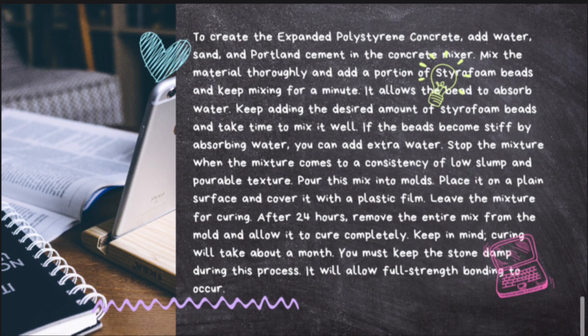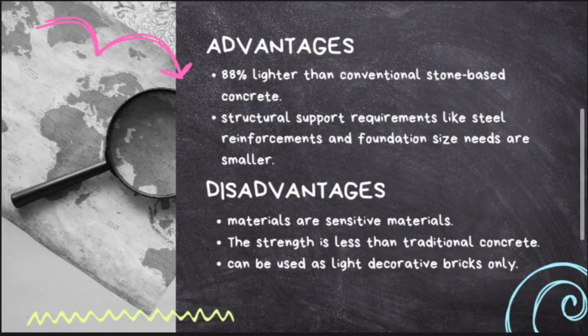After 24 hours, remove the entire mix from the mold and allow it to cure completely. Keep in mind, curing will take about a month. You must keep the stone damp during this process. It will allow full strength bonding to occur. The advantage of polystyrene concrete is it is 88% lighter than conventional stone-based concrete. Its structural support requirements, like steel reinforcement and foundation size, are also smaller than average.